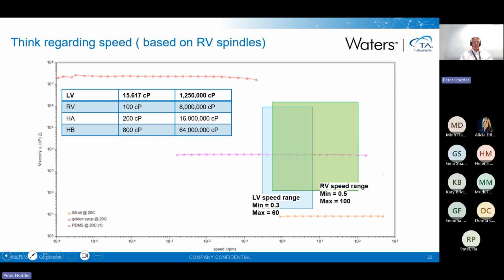So could the RV. And in fact, when we come to look at the HA and HB, we can see that, yes, we might just be able to measure the golden syrup, but we can't actually reach high enough to measure the PDMS, the polymer melt, purely because that sample misbehaves. It starts to really not represent a sensible sample by any chance. It will basically create a hole and cavity. So what we've got is that actually, if we consider speed or consider the torque ranges, we have a little complicated story to make sure we hit the right region to be able to get a decent measurement.